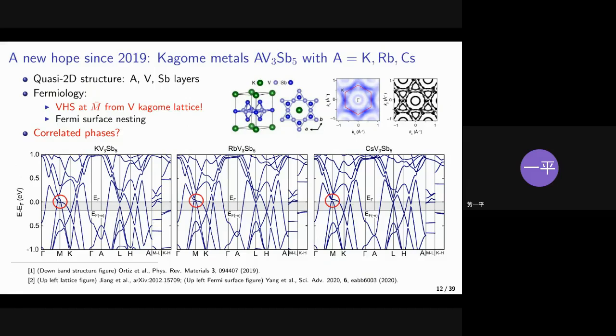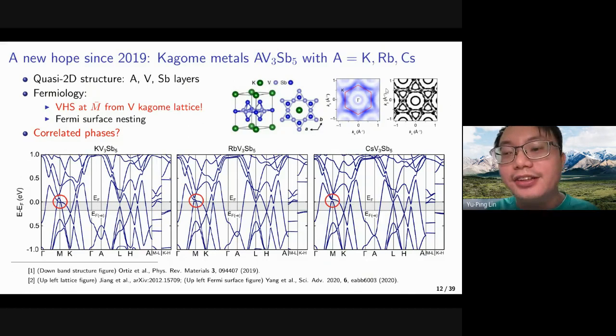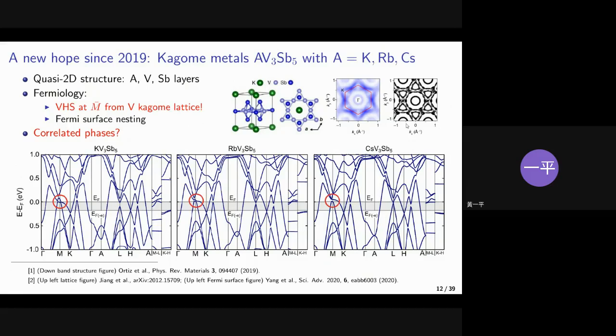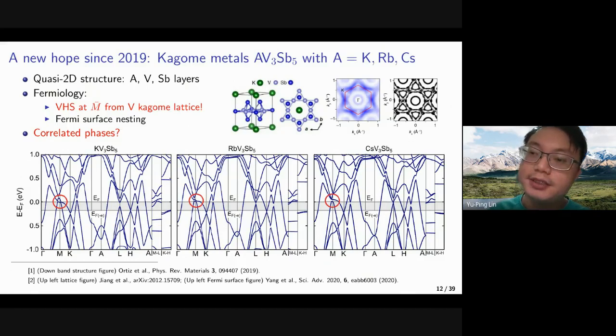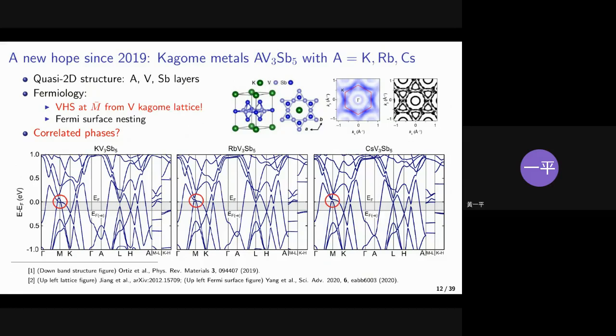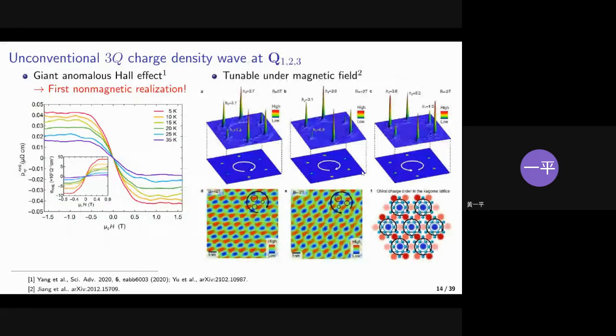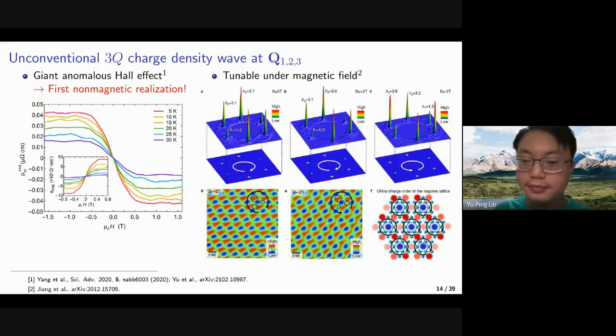Can I ask a question since you are at this point? In this slide, the upper right part, there's a color density plot for electron density. Is it measured by experiment or? So this one is from ARPES. I see. And this one is from first principle calculation. Usually, can ARPES see the charge density directly, or do they need to do some manipulation? Because I think usually with ARPES you just see the bands. Yeah, but I think they can see the Fermi surface. I see. So in principle, if they can do ARPES, does that mean they can also do some kind of STM to see this real space pattern? Yeah. Not in the momentum space, but I think this one was obtained from STM. So it's a real experiment.